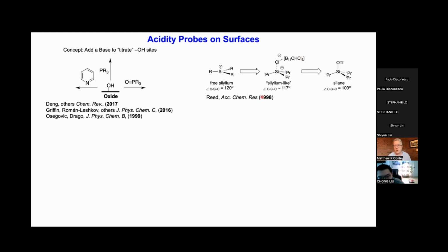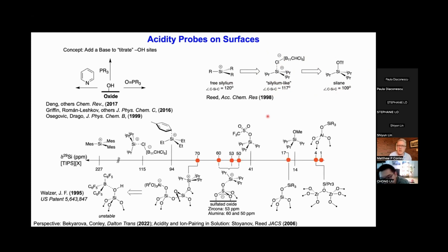And this is where a lot of the controversy about silylium ions resulted in the early to mid 90s, where you start to distort from this pure sp2 hybridization to something that's in between here and the fully sp3 silane species. And it turns out the silicon NMR chemical shift of those species is all related to one another.